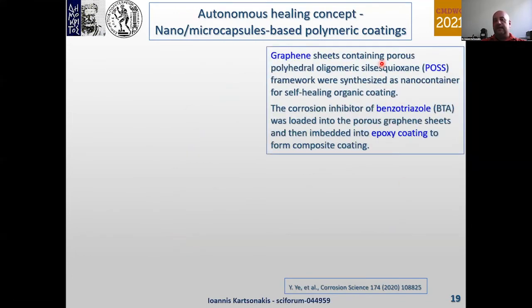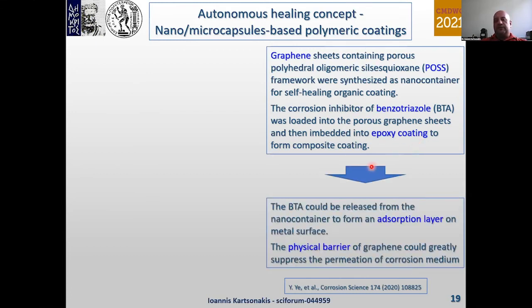In the work of Ye in 2020, graphene sheets containing a porous polyhedral oligomeric silsesquioxane framework were synthesized and were used as nanocontainers for self-healing organic coatings. These nanocontainers were loaded with the organic inhibitor benzotriazole, and the final composite was incorporated into epoxy coating. The benzotriazole could be released from the nanocontainers to form an adsorption layer on the metal surface after the crack formation, and the physical barrier of graphene also could greatly suppress the permeation of the corrosion medium.